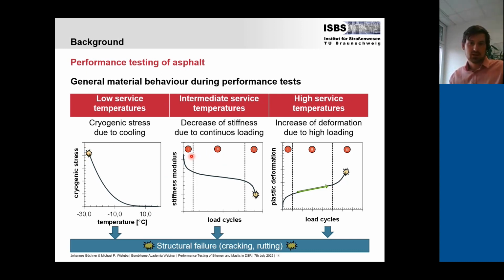At intermediate temperatures, we see a decrease of the stiffness due to continuous loading. So here's the stiffness modulus. We have 3 distinct phases, a quasi-static phase in the second part, and then also the failure phase, where we also see the cracking. And in the high temperature range, we usually look at some kind of deformation of the material due to high loading or repeated loading. Here we show the plastic deformation, also 3 very distinct phases, which can be determined by different performance tests. And also here we have the 3rd failure phase, where we see rutting and destruction of the material behavior.